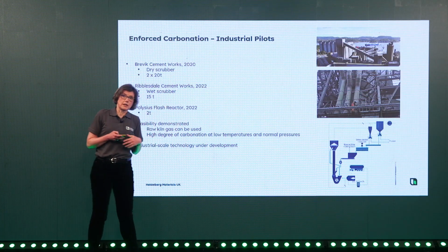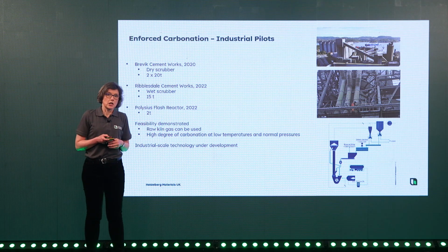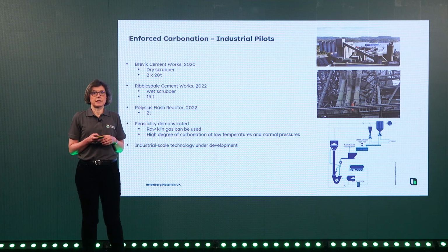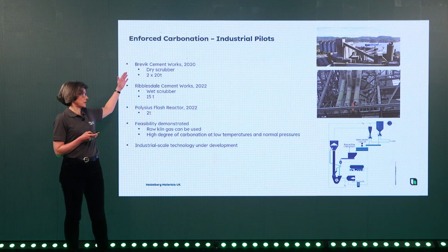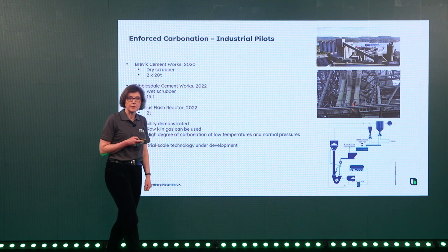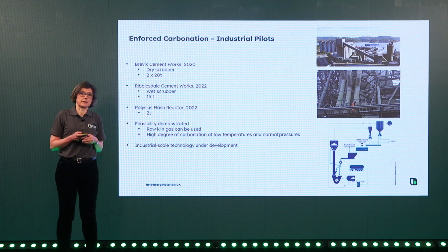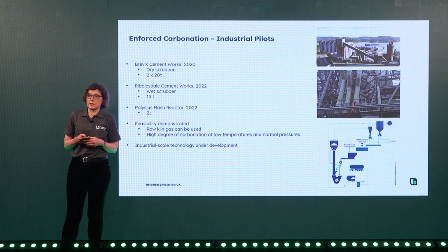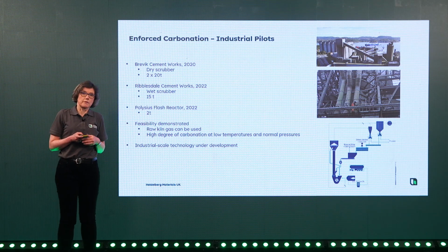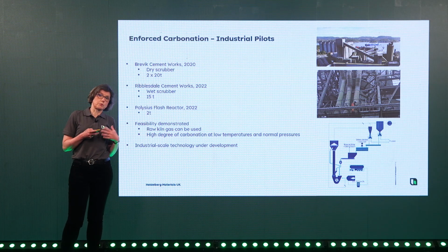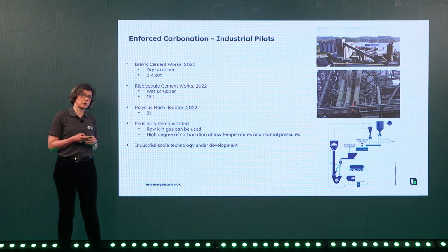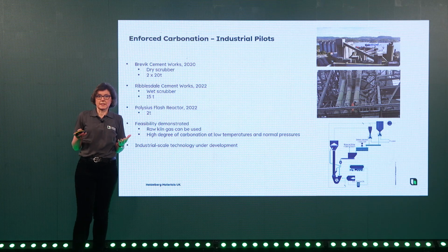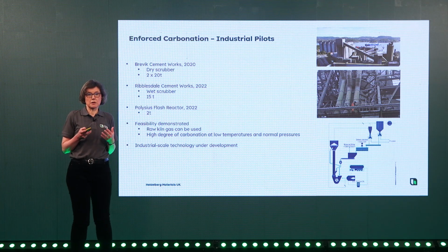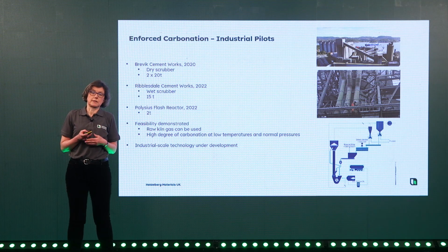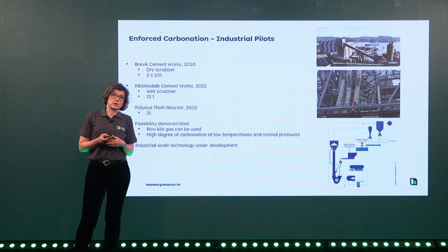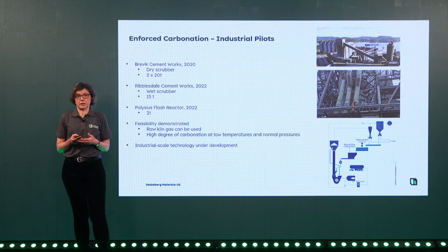From the selective separation, we then took this paste to industrial pilots. The first one was carried out at our cement works in Brevik in Norway in 2020, where we have a dry scrubber associated with the cement plant, which you can see there on the top of the slide. And we created 2 times 20 tons of carbonated RCP. Then we repeated this in our own cement works in the UK in Ribblesdale in 2022, where we also have a scrubber, but it's a wet scrubber, and we produced 15 tons there. And then we did a smaller trial in Germany on a Polysius flash reactor. What have we shown by this? It was really showing the feasibility of being able to use raw kiln gases to carbonate the paste, and that we achieve a very high degree of carbonation even at low temperatures and at normal pressures.